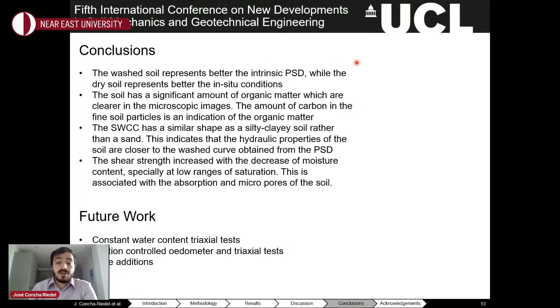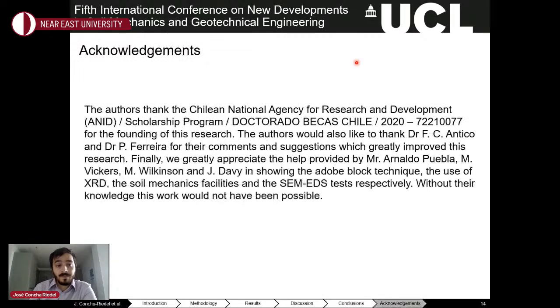And finally, the shear strength increased with the decrease of moisture content, especially at low ranges of saturation. This is associated with the absorption and micropores of the soil. For the future, it is planned to perform constant water content triaxial tests, suction controlled oedometer and triaxial tests, and also to add fiber to the mixture.